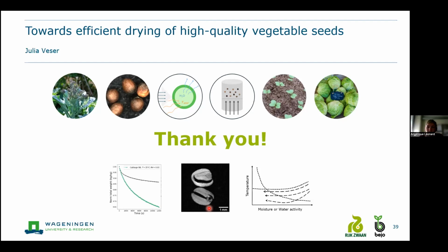Okay, and concerning your model, do you consider that it's homogeneous concerning internal diffusion, the same coefficient everywhere, or does it depend on the location inside the seed? Yeah, for the first basic model, we assumed it's constant everywhere. We only distinguish between the inside and the outside, because we have a thin coat around the seed, and that's quite a different tissue than the inside embryo. So there we make a distinction between the two diffusion properties. But within the whole embryo inside, at the moment, we assume it to be constant. We hope that, by including this porosity or air layer development in the model, we can describe the data already well enough. But of course, a next step would be to say, okay, there are different tissue layers, perhaps we need to take that also into account.